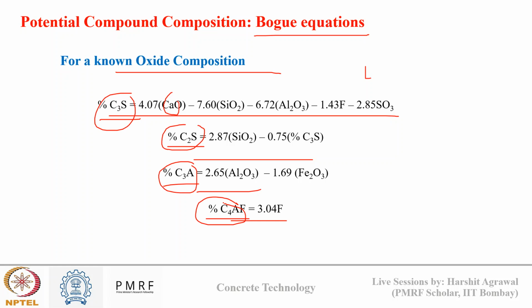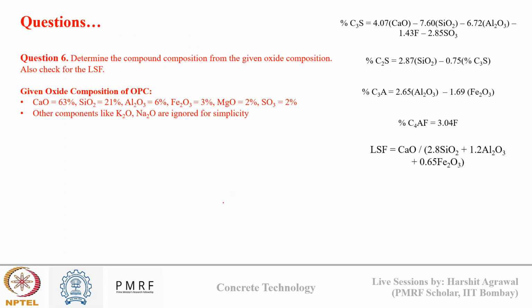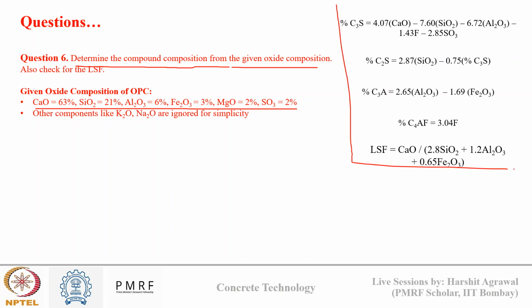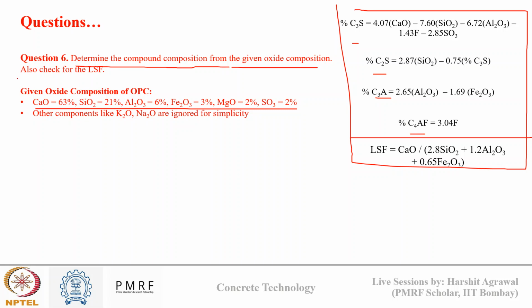So just give it a try. How to use this equation? I have this question for you, where you need to determine the compound composition of the cement for the given oxide composition. This is the oxide composition that I have given to you. Use these sets of equations and determine the proportion of C3S, C2S, C3A, and C4AF. Also check the lime saturation factor. Is it greater than 1 or less than 1?